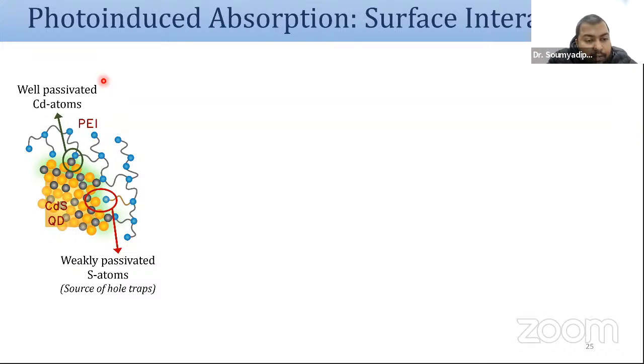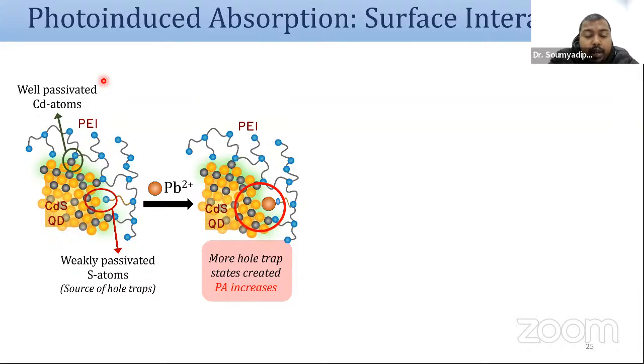Now, in the case of cadmium sulfide quantum dots, you see that PEI is very well passivated at the surface of the quantum dot, and it can bind well with the cadmium 2+ ion, but it does not bind well with the sulfur ions, which are weakly passivated at the surface. That gives lead 2+ ion access to the surface sulfur atoms. When it has access to the sulfur atoms at the surface, we are creating more hole trap states.